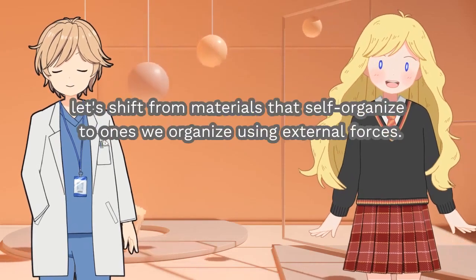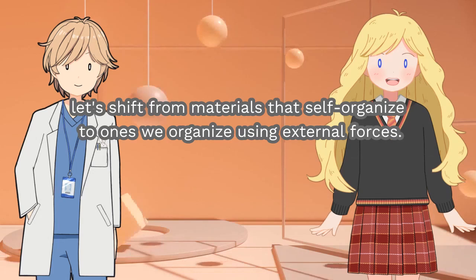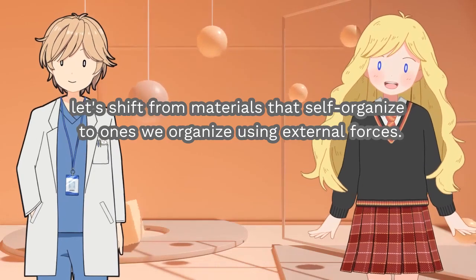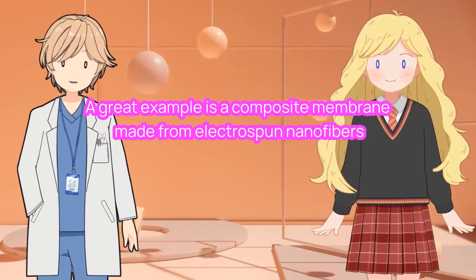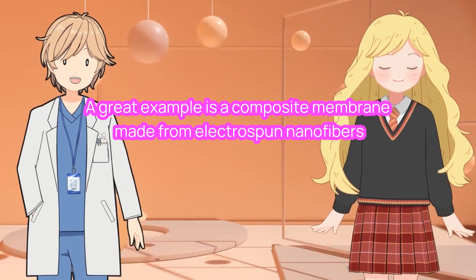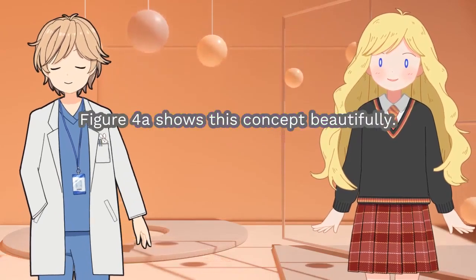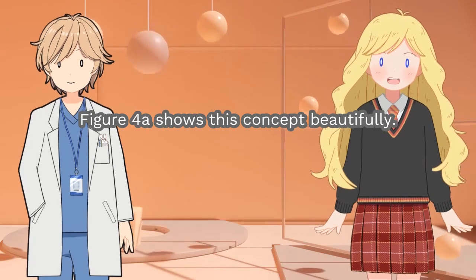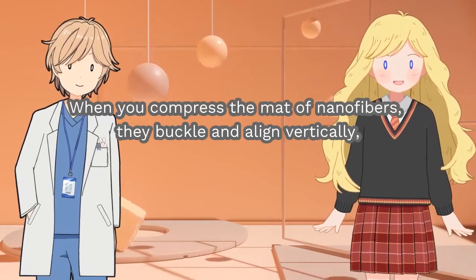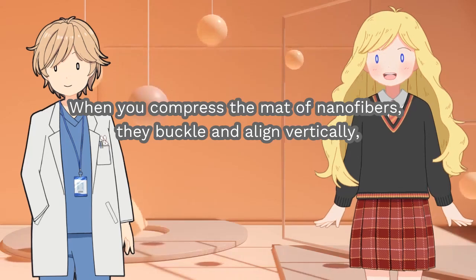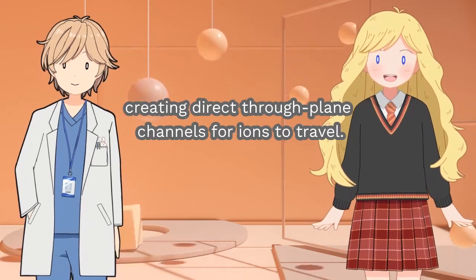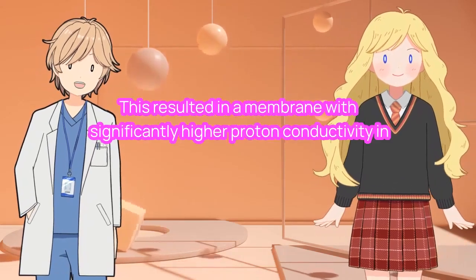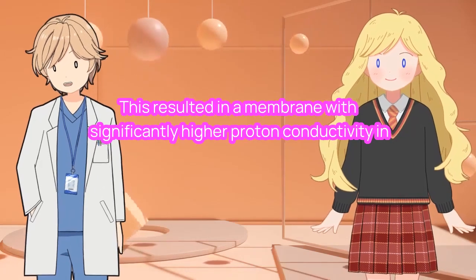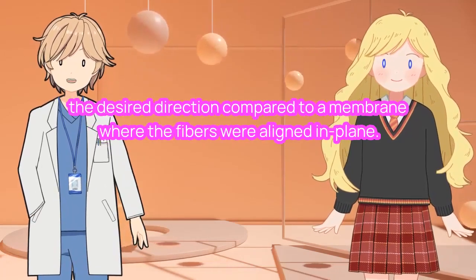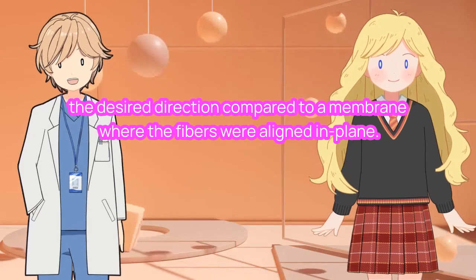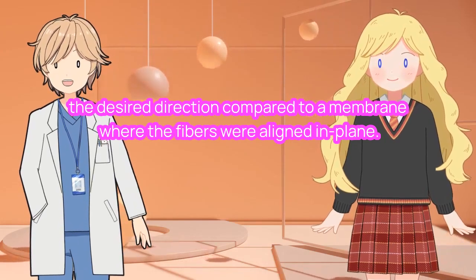Now, let's shift from materials that self-organize to ones we organize using external forces. A great example is a composite membrane made from electrospun nanofibers, which are then compressed. Figure 4a shows this concept beautifully. When you compress the mat of nanofibers, they buckle and align vertically, creating direct through-plane channels for ions to travel. This resulted in a membrane with significantly higher proton conductivity in the desired direction compared to a membrane where the fibers were aligned in plane.